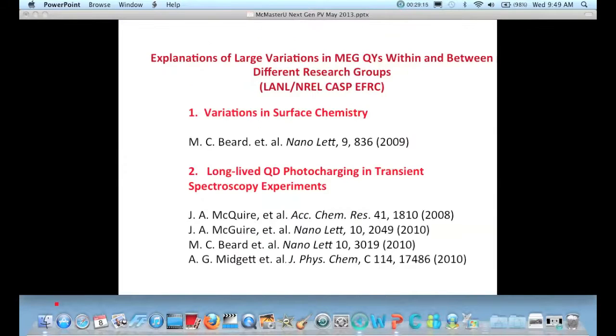It turns out that this is due to variations in the surface chemistry between groups looking at this, because the surface in a quantum dot is a very high percentage of the total atoms. If it's 5 nanometers or so, 30% of the atoms are on the surface. So surface chemistry plays a big role in determining how the relaxation dynamics go. Secondly, when you have a high-energy photon, there's a probability of trapping an electron on the surface. If it gets trapped and is long-lived, then when the next pump pulse comes along, it will see not a neutral dot, but a charged dot. That charged dot also has an Auger-like characteristic, and this confounds the results.